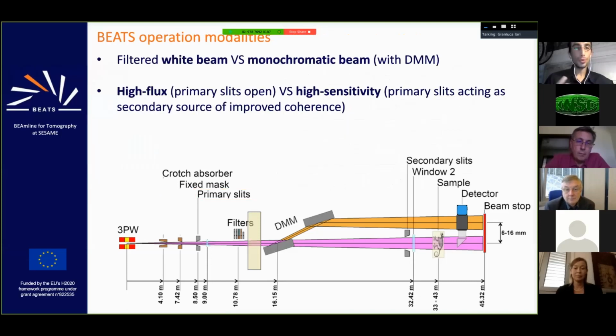To conclude on this part, we said that there are two modalities depending on the energy requirements. So white beam versus monochromatic beam. White beam for fast applications, a high number of photons. Monochromatic beam to tailor the energy. Again, when we work in absorption and we just care for the flux, we leave the primary slits open and we work at high flux. When we want to use phase contrast and increase the coherence of the radiation, we close the primary slits that act as a secondary photon source.